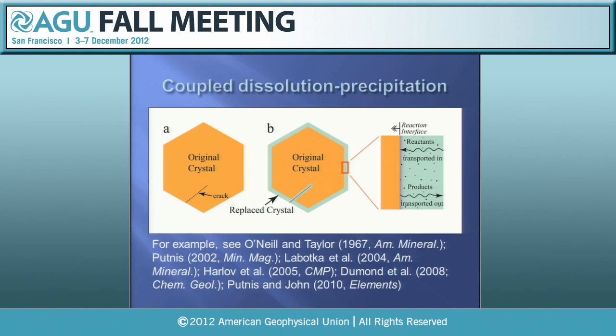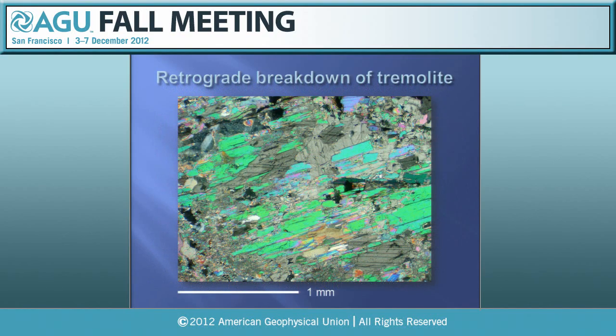So it's a type of pseudomorphing, if you will, and it's been studied and documented now in this series of really, really extraordinary papers and related ones. All right? So if we go back to our poor tremolite, you can see that there's really been no volume change. There's no cracks. There's nothing obvious. What looks like happened is that the dolomite got in here and replaced the tremolite along cleavages and so forth, and more or less isovolumetrically, suggesting some sort of coupled dissolution precipitation.